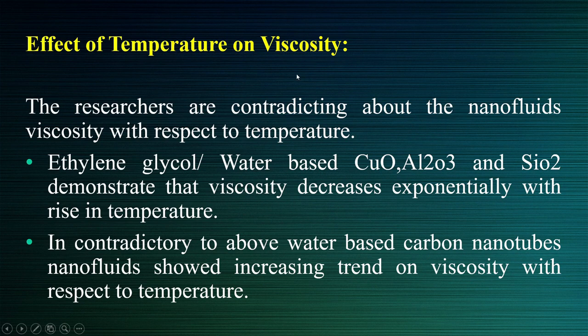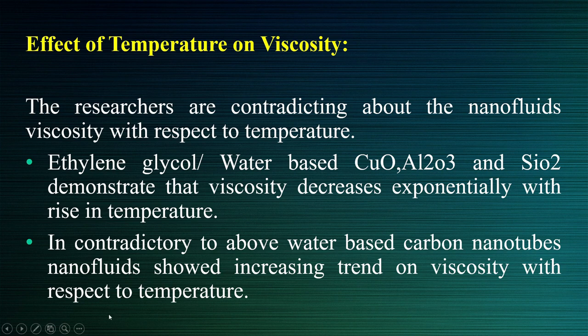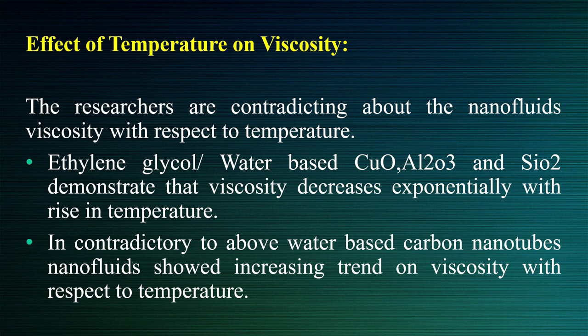Regarding the effect of temperature on viscosity, for base fluids of ethylene glycol and water with CuO, Al2O3, and SiO2 nanoparticles, viscosity decreases exponentially with rise in temperature. However, water-based carbon nanofluids show an increasing trend of viscosity with temperature. Again there is no fixed relation — it depends on which nanoparticle and base fluid combination is used, the volume concentration, and the particle size.